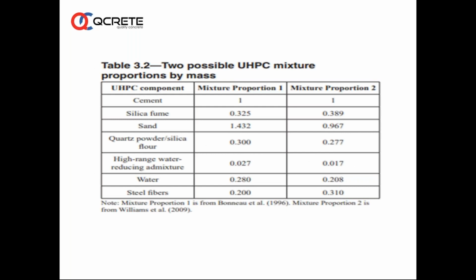So this is from ACI, where they have given two possible UHPC mixture proportions, and you can see here a huge amount of silica fume, which, as we discussed earlier, has become part and parcel of these kinds of mixtures. And you have sand, quartz powder, high range water reducing admixture, water and steel fibers. So these two have been given, and these can be used as starting points for making ultra high performance mixtures using the locally available materials.